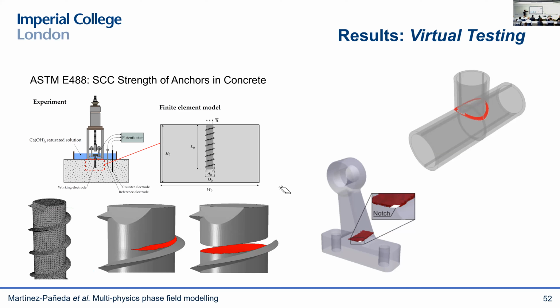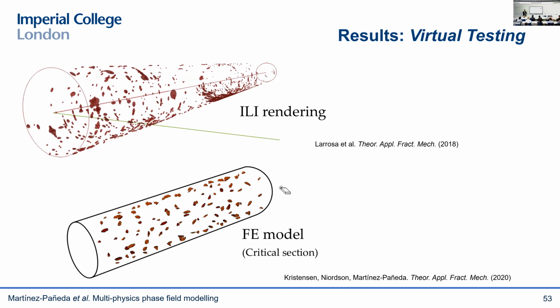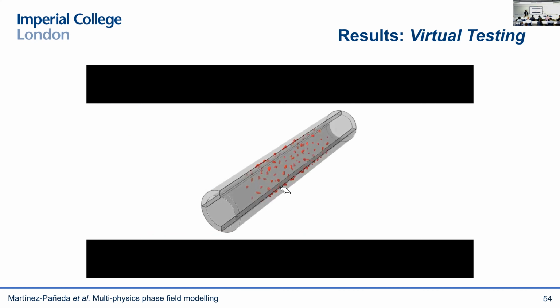So we can do standardized lab tests, but we can also do large-scale calculations that bring this idea of virtual testing to hydrogen containment. And more exactly, we can also couple this with inspection. So we can create sort of a digital twin of critical infrastructure. So you can see, for example, here, this is a 12-kilometer pipeline operated by BP that had multiple defects, pitting corrosion, all these red dots are defects. We can introduce those defects into a model. Remember, the phase-field is a degree of freedom, so this could be an initial condition on certain nodes in the phase-field, no need to have any special functionalities. And then we can just load our pipeline to the in-service conditions, and then we can see how those defects eventually start growing, how they eventually merge with each other, and then how they eventually propagate and expand, introducing the complete failure of the pipeline.